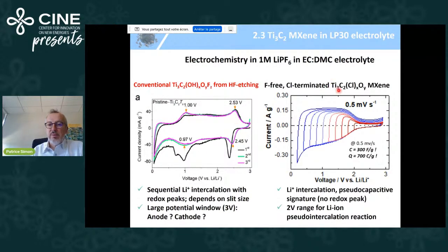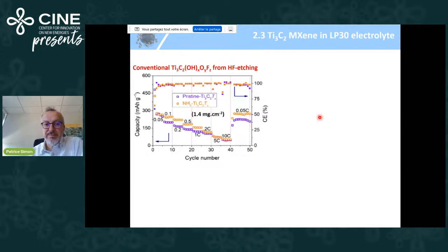And this is our CV obtained with fluorine-free, chlorine-terminated MXenes. You can see that we have a very symmetric cyclic voltammetry. It goes from 2 volts down to 0.2 volt. It's a 2 volt range for lithium intercalation. The average potential is 1.2 volt for lithium intercalation, which is compatible with a negative electrode. But here, you can see that you have a capacitive-like signature.